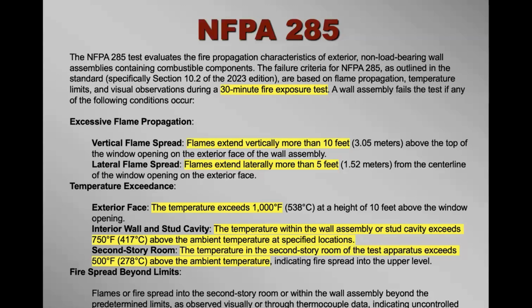So the flame can't spread vertically above the window opening more than 10 feet, and it can't spread laterally more than 5 feet on either side of the window opening in the assembly. The exterior facade temperature, if it exceeds 1,000 degrees, it fails. I'll show you later that a lot of these FRPs burn at 1,000 degrees, but more importantly, they melt at a much lesser temperature. The temperature within the assembly can't exceed 750 degrees, and the temperature in the second story room can't exceed 500 degrees. So this is all the failure criteria that NFPA 285 requires.